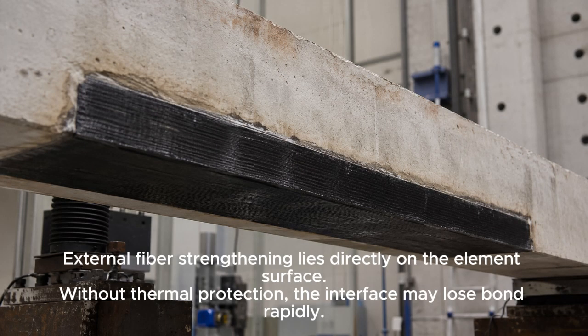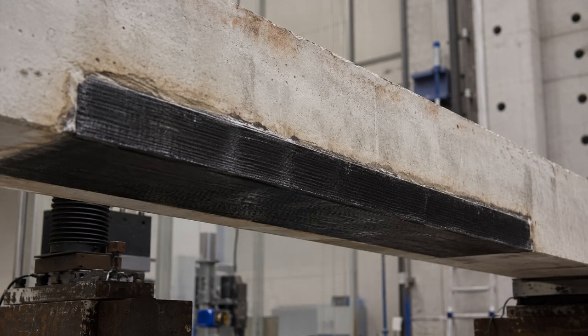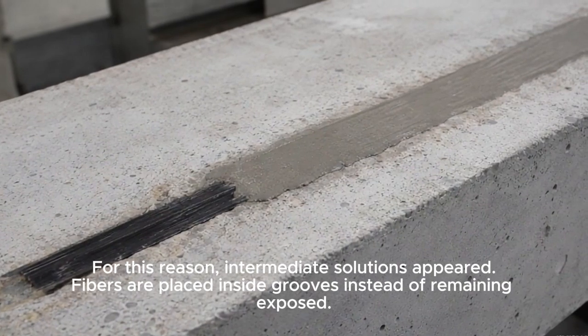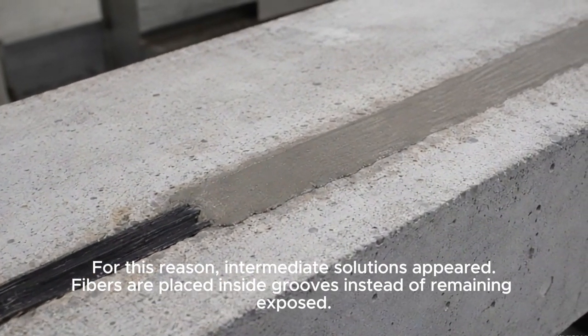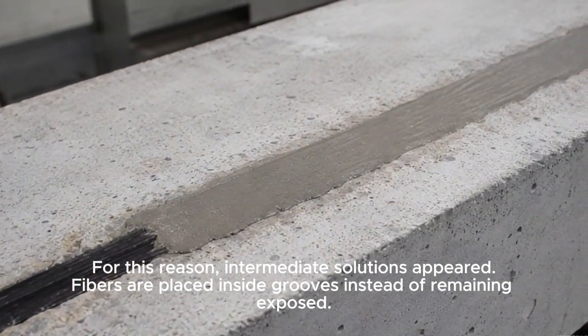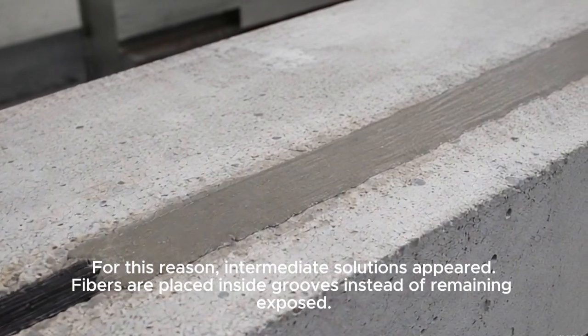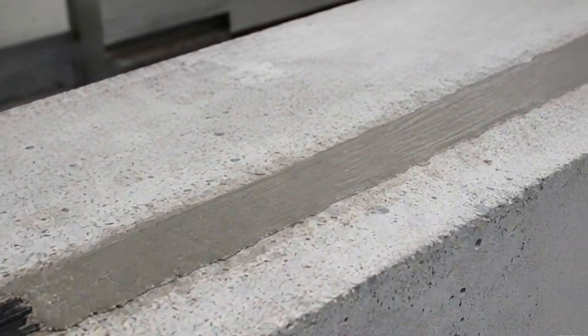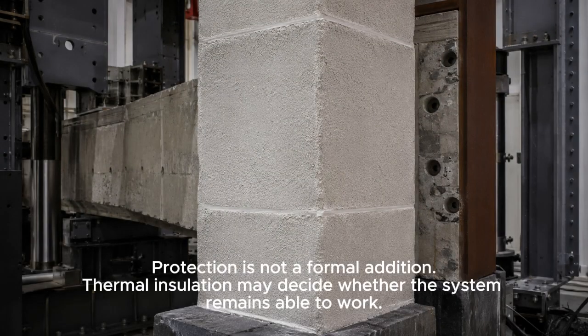External fiber strengthening lies directly on the element's surface. Without thermal protection, the interface may lose bond rapidly. For this reason, intermediate solutions appeared. Fibers are placed inside grooves instead of remaining exposed. Protection is not a formal addition. Thermal insulation may decide whether the system remains able to work.